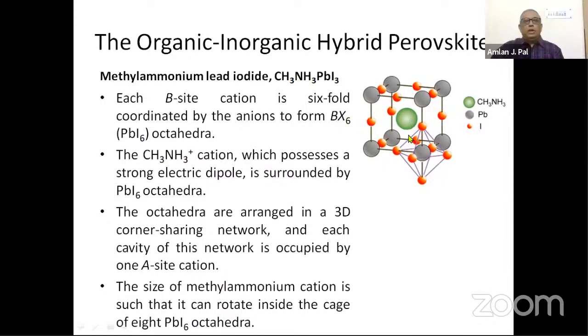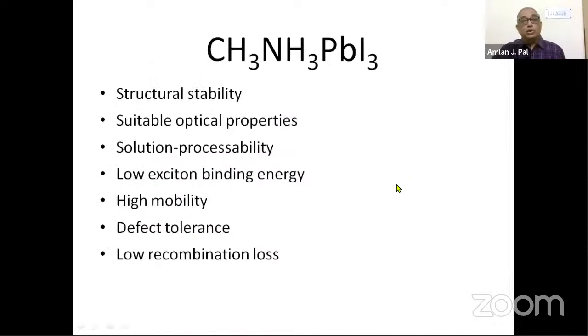So what are the beautiful properties for solar cell applications that we have for methyl ammonium lead iodide? I will show you why they are structurally stable, and why the optical properties are so suitable. It is solution processable, because I will show you that this material can be made in the lab through a solution method. It has very low exciton binding energy, and as you now understand, low binding energy means I will be able to dissociate the exciton, so charge separation should be much easier. High carrier mobility, because even if I can separate the charge carriers, I won't be able to take them out without it.